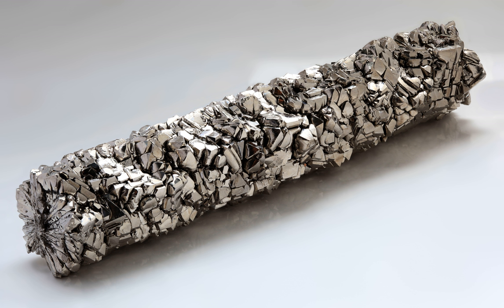Titanium tetrachloride plus 2 magnesium yields titanium plus 2 magnesium chloride at 1100 degrees Celsius. About 50 grades of titanium and titanium alloys are designed and currently used, although only a couple of dozen are readily available commercially. ASTM International recognizes 31 grades of titanium metal and alloys, of which grades 1 through 4 are commercially pure, unalloyed. Those four vary in tensile strength as a function of oxygen content, with grade 1 being the most ductile, lowest tensile strength with an oxygen content of 0.18%, and grade 4 the least ductile, highest tensile strength with an oxygen content of 0.40%.